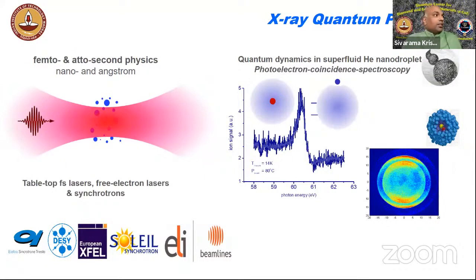So a couple of representative results are here. On the left is the theme of these experiments, where we take angstrom or nanoscale matter, which are in free jets, and laser pulses spanning all the way from near infrared up to the X-rays can be focused onto these in order to realize correlated and collective dynamics. As the right panel here shows, we have this very strangely shaped spectral peak, which has a maximum and also a negative dip. So this is textbook atomic physics, but then there's a very ubiquitous phenomenon called the Fano resonance. So this is just a benchmark result from our work.